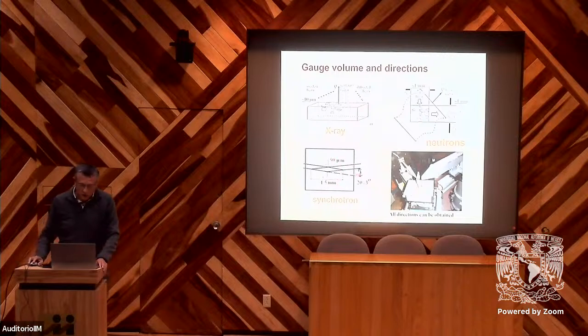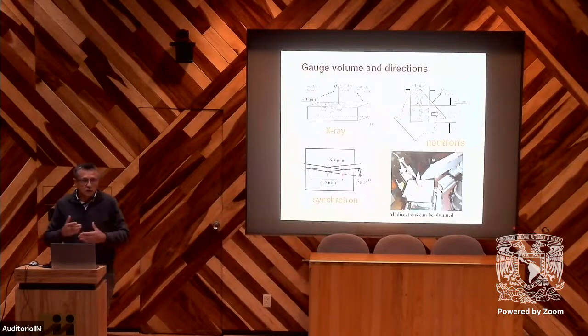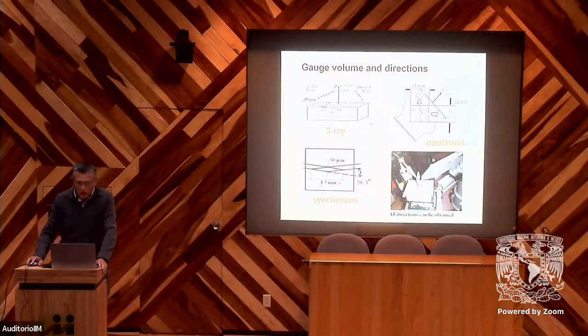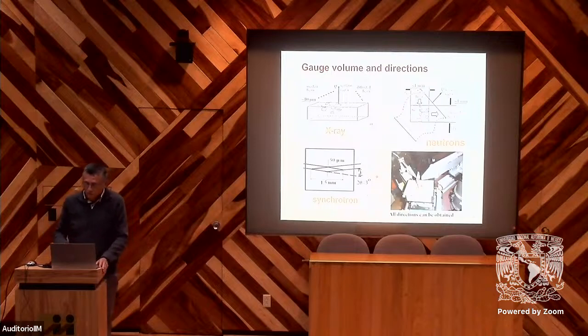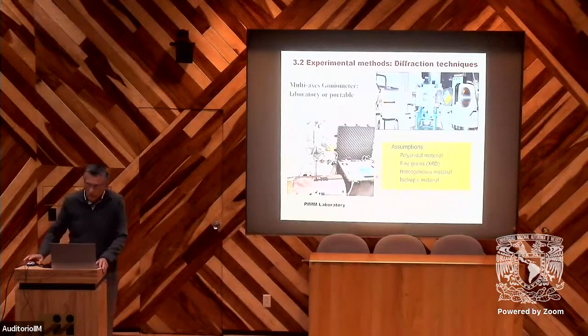The advantage of the synchrotron is that we have a very high intensity. That means we can measure in a very small fraction of the material. For example, if we have some particles, we can measure in these particles. The inconvenience is that the Bragg angle is very low. So that means it is not sensitive enough, but we can use it.